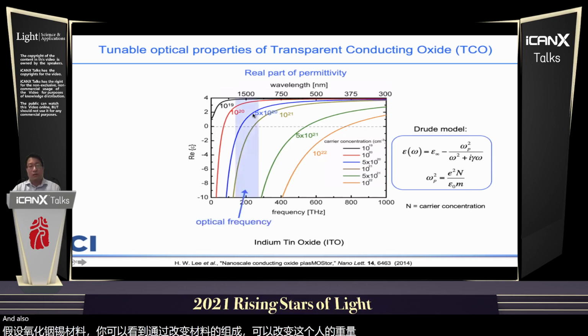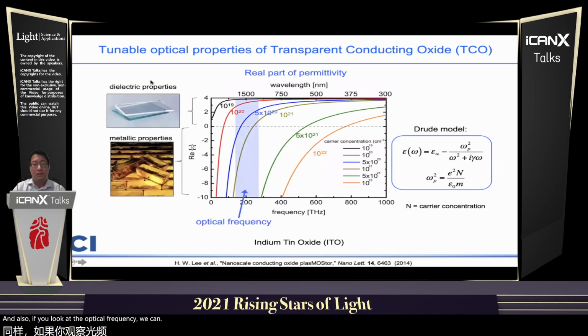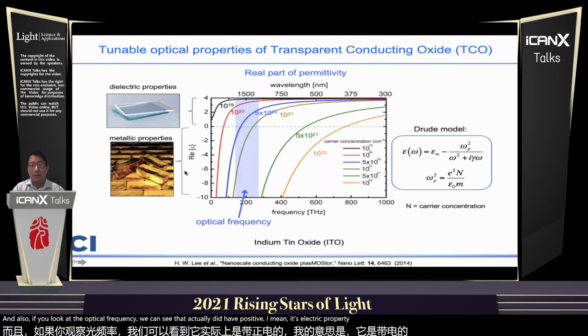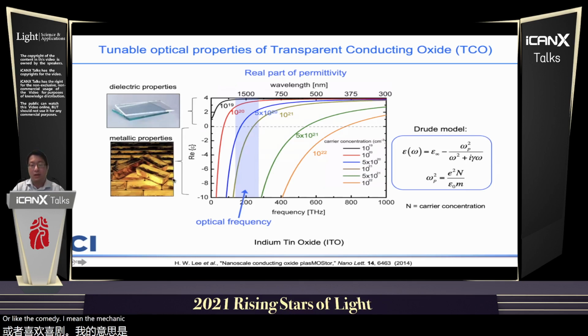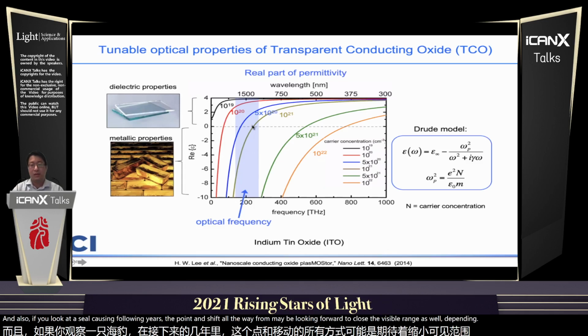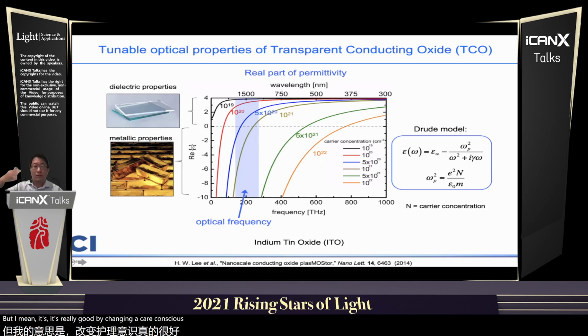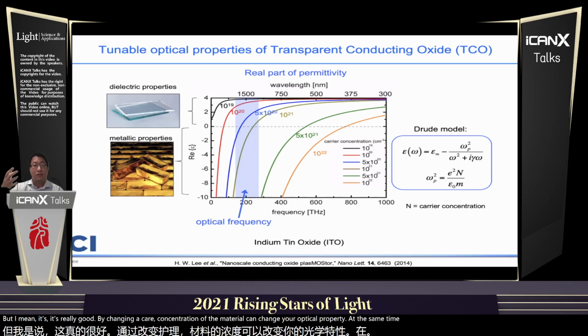And also, if you look at the optical frequency, you can have a positive permittivity, which means a dielectric property, or negative permittivity, which means a metallic property, depending on the carrier concentration of the material. And if you look at the zero crossing point, the ENZ point, you can shift all the way from maybe near infrared to close to the visible range as well, depending on the carrier concentration. So that means it's really good. By changing the carrier concentration of the material, you can change the optical property, at the same time changing, for example, the ENZ property of this material.